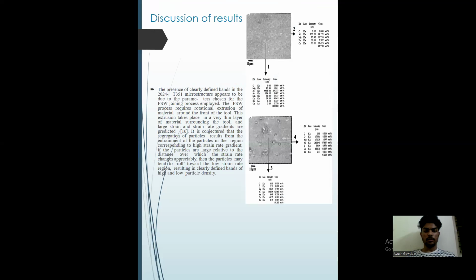Discussion of results. The presence of clearly defined bands in the 2024-T351 microstructure appears to be due to the parameters chosen for the FSW joining process employed. The FSW process requires rotational extrusion of material around the front of the tool. This extrusion takes place in a very thin layer of material surrounding the tool, and large strain and strain rate gradients are predicted. It is conjectured that the segregation of particles results from the entrainment of the particles in the region corresponding to high strain rate gradient.